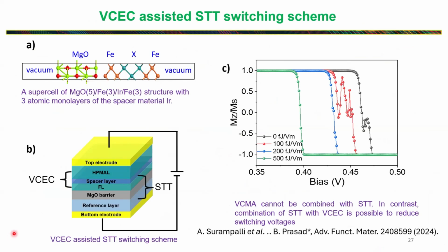then one can actually integrate this with STT. VCMA you can't integrate with STT, but this one you can. So with that, you can reduce the STT switching. So basically, this can assist STT to switch at lower current, and that way it can actually work for low dimension devices. Because as I told, one of the problems is that you need a higher current to switch the devices at lower CD, and that creates a Joule heating effect. But if you incorporate VCEC with that, then that is possible.